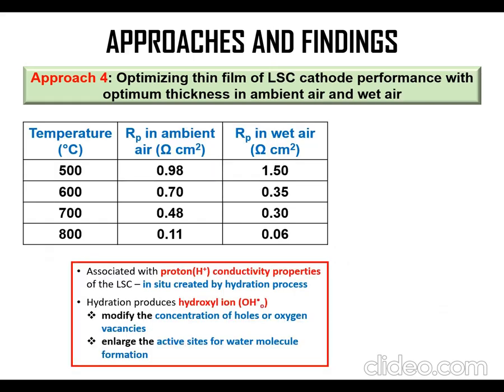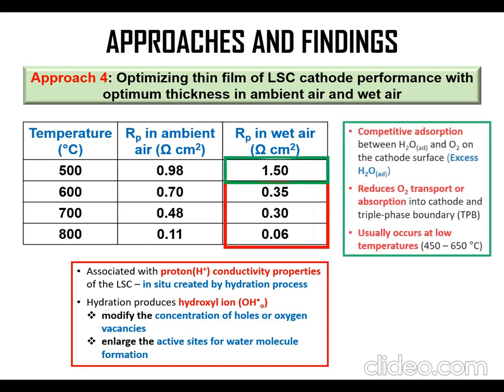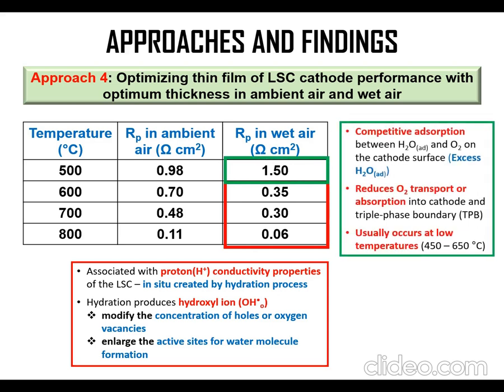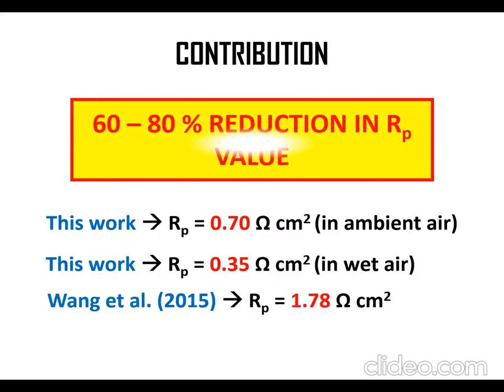Approach number 4. We measure the performance of the LSC thin film in different air, which are ambient air and wet air. As we can see from the results, the RP values in wet air are lower than the RP values in ambient air at temperatures from 600 to 800 degrees Celsius. However, at temperature 500 degrees Celsius, the RP value in wet air is higher than the RP value in ambient air. From the overall results we obtained from this work, we managed to reduce the RP value of the LSC cathode at intermediate temperature by about 60 to 80%.